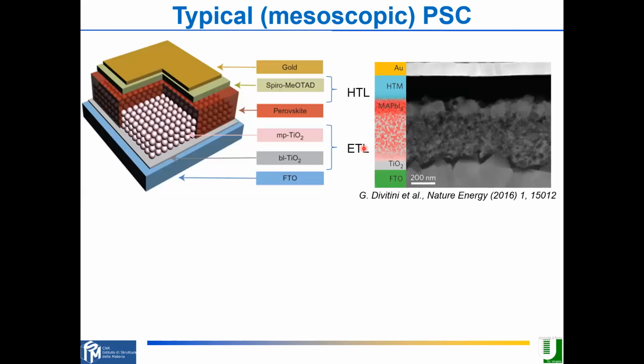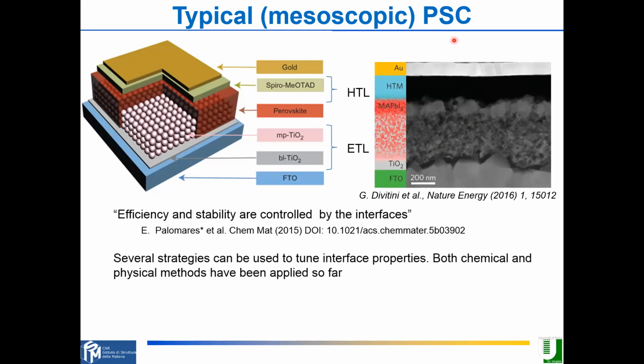Okay, so this is just a sketch of the mesoscopic version of the solar cell. This is a 3D image we did some time ago. And then you can see there is a mesoporous region. The perovskite is also in the mesoporous region of titania. Then there is an overlay, and then the electron and hole transporting layers. So as you can see, there are a lot of interfaces. And as Emilio Palomares said some time ago, efficiency and stability are really controlled by the interfaces, which is quite conventional for any electronic and optoelectronic device nowadays. So it's very important to master and to tune these interfaces.